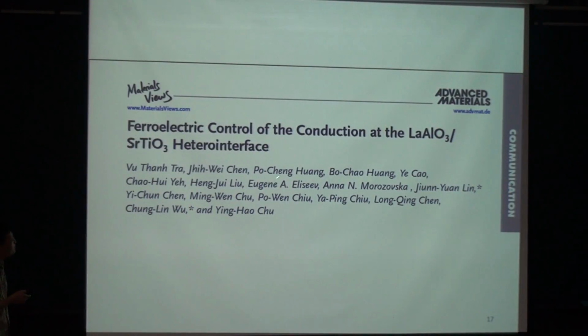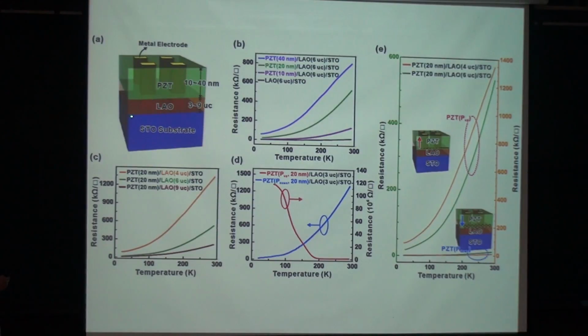Three years ago, with the help of Professor, we also did something on a similar thing. This sample was prepared by my PhD student in Professor Jiunn-Yuan's lab, and we do not answer why this heterostructure is conducting, but we try to find a new way to manipulate the conductivity of this device. So what we do is, in addition to this bilayer, we put a PZT top layer on it. And because PZT is a ferroelectric material, once we can control the direction of polarization in PZT, for example, when the polarization is up, this bilayer is actually insulating.